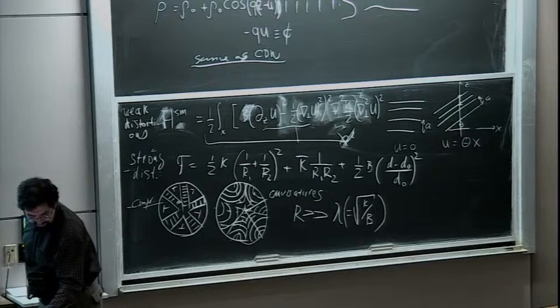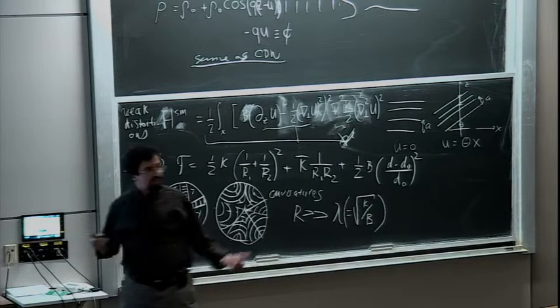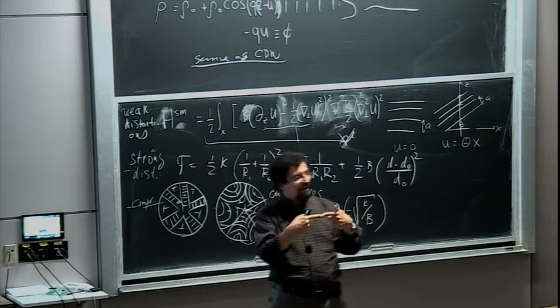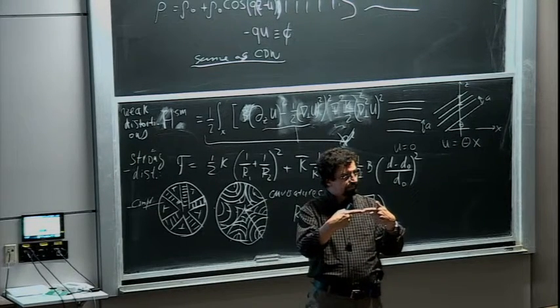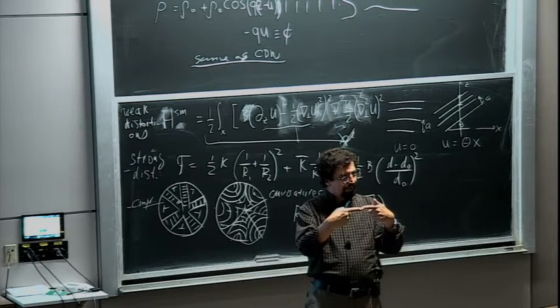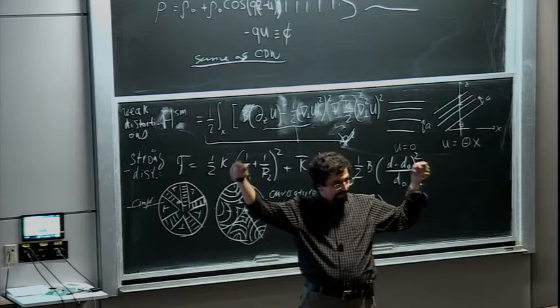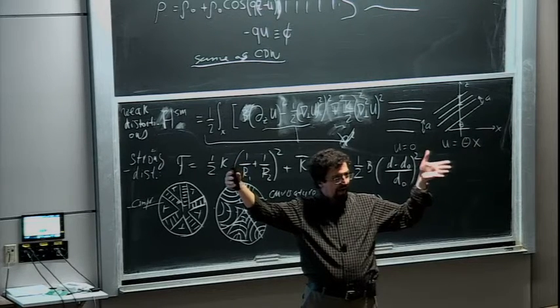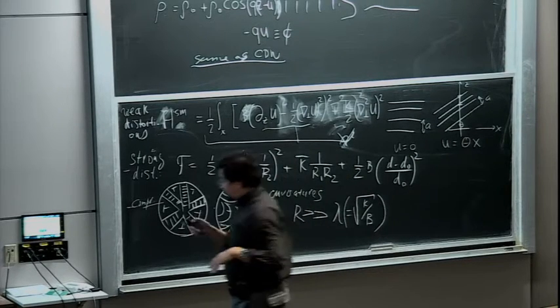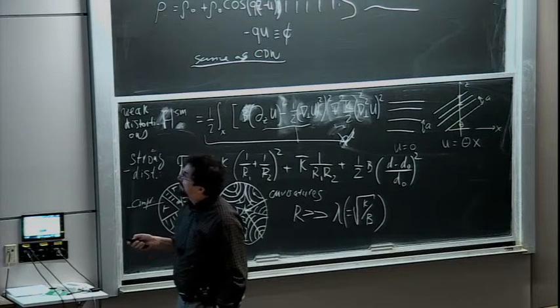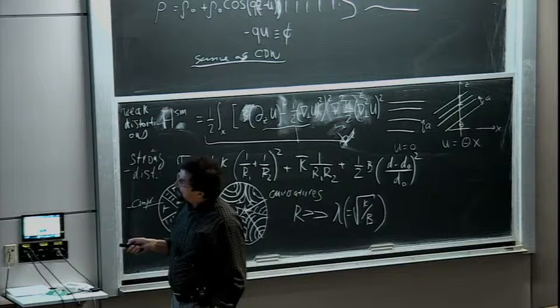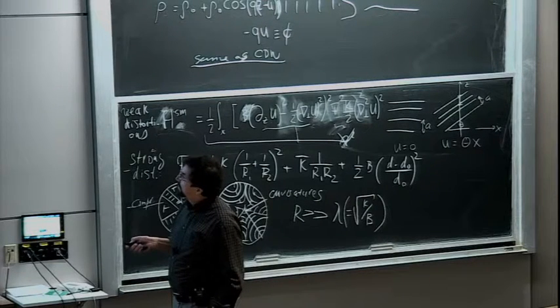And then since this distance is nothing else but the two radii of curvature, right? Because the radii of curvature start at the focal lines. That's why the focal lines are focal lines. So you have the opportunity to introduce the third coordinate, which is r, which simply separates one layer from the other.